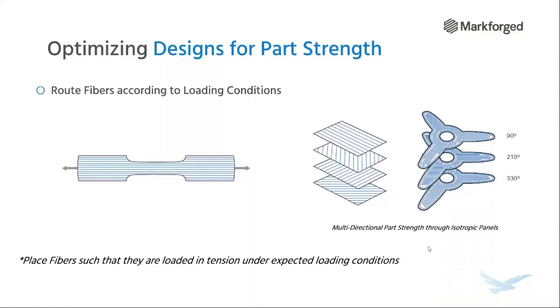On the right side of the screen, we see an isotropic part that has several isotropic panels that are rotated at specific degrees. And in this case, we have a part with 3 fingers. And notice how every third panel, the fibers are laid out in the direction of one of the fingers. And with the software that comes with Markforged systems, you're able to do that, to actually route the fibers so that every third one, whatever it is, let's say you had 4 fingers, you're able to do the same thing by changing the angles. And what that does is it's going to make it much stronger in multiple directions. And notice how we have each panel there alternating angles as it goes up. And so that's the first tip, to place fibers so that they're in tension.